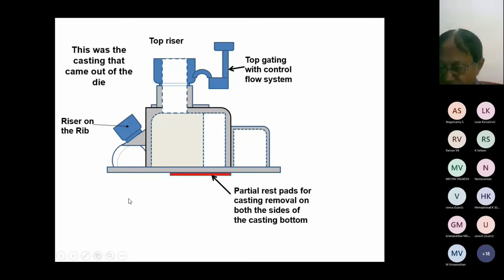And we found this die was working very well. In the old design, the fettled weight remains the same for both the old and new designs. The shot weight here is 2.1 kg. This is hardly 1 kg. And the yield, here 34.3%, is now 68.5%. We got nearly double. The old design requires 2 operators and here only 1 operator. And the output has also gone from 15 to 21 numbers per hour. It's a great success, such a top gating.